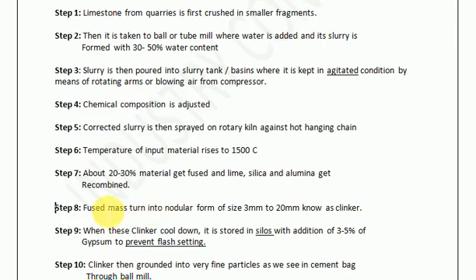In step 8, the fused mass turns into a nodular form of size 3 mm to 20 mm, known as clinker. In the rotary kiln at very high temperature, the material from the slurry tank is sprayed in, its temperature is raised, the material gets fused, and this fused material converts into nodular form — particles with an average size from 3 mm to 20 mm — and this is known as clinker.